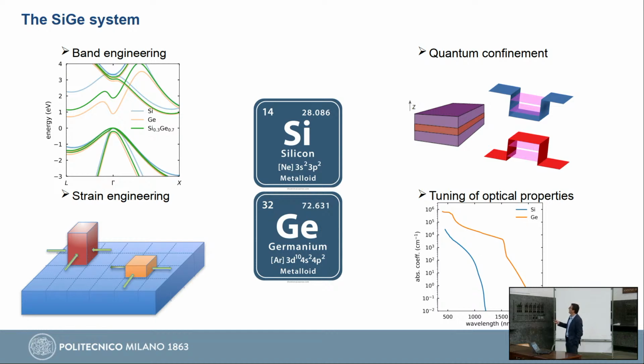So for example, here I have the absorption coefficient of silicon and germanium. We see that silicon at its band edge is a poor absorber, so the absorption coefficient is very low. So I need to go to quite a short wavelength to have some relevant absorption, and it's essentially transparent above 1100, 1200, so 1200 nanometers. Instead, germanium is a very strong absorber in the infrared. Actually, this kink in the absorption exactly corresponds to 1550 nanometers, which is a key wavelength in telecommunication.